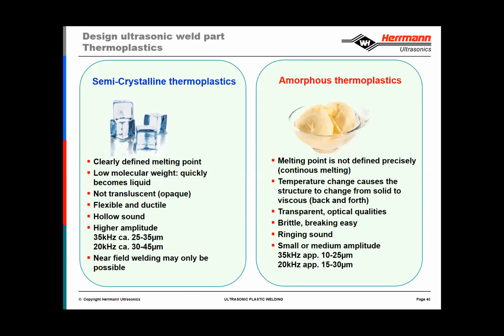So amorphous thermoplastics typically have a metallic ringing sound. So if you took an amorphous part and dropped it on a table, you would hear that ringing sound. Again, just a way to identify an amorphous over a semi-crystalline material. And as you can see, they typically have lower amplitude requirements. In 35 kilohertz, the range is about 10 to 25 microns of 0 to peak. And in 20 kilohertz, the range is about 15 to 30 microns.